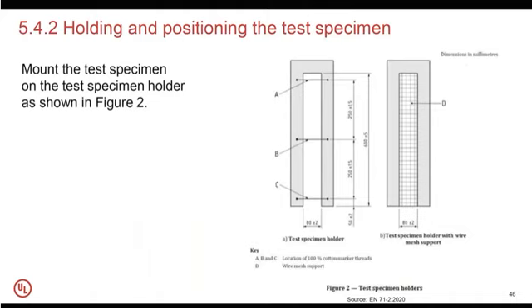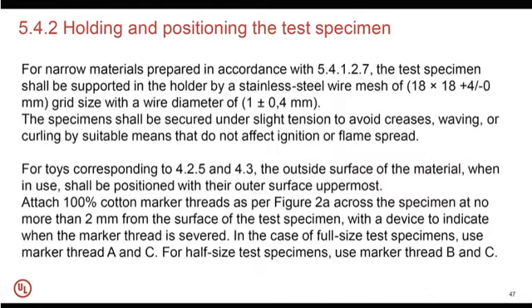And this is holding and position of the test specimens. So there are, again, clear figures which demonstrate how to mount the test specimens on the test specimen holder. For narrow material, which are prepared in accordance with 5.4.1.2.7, the test specimen shall be supported in the holder by a stainless steel wire mesh of 18 per 18 plus 4 minus 0 millimeter, grid size with a wire diameter of 1 plus or minus 0.4 millimeter. So the specimens shall be secured under slight tension to avoid creases, waving or curling by suitable means that do not affect ignition or flame spread.